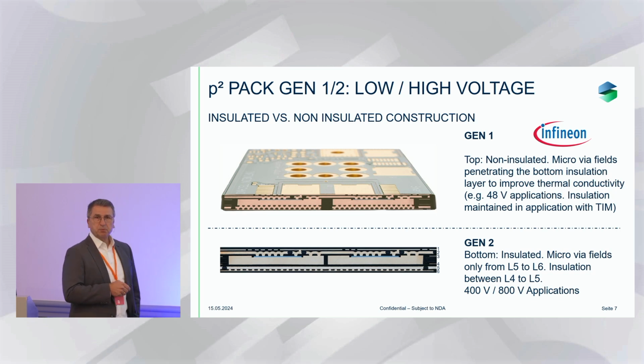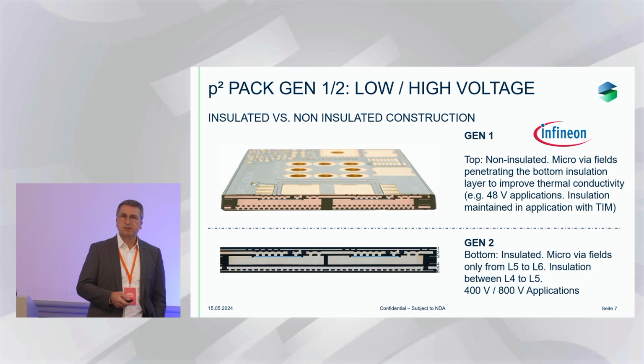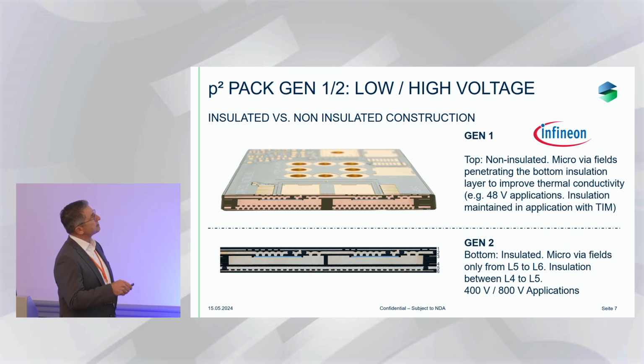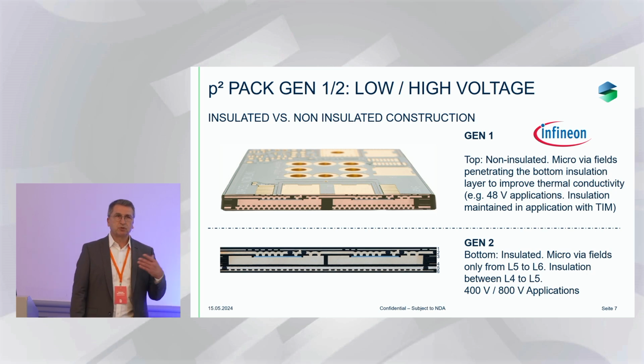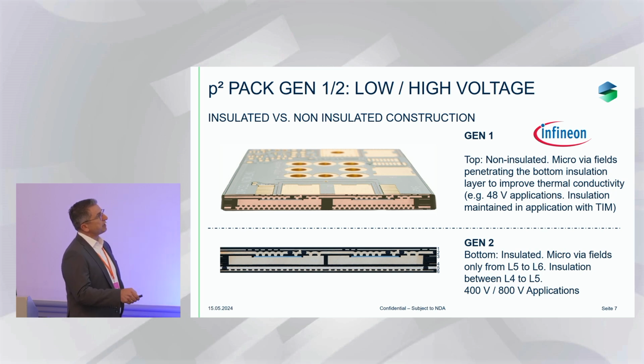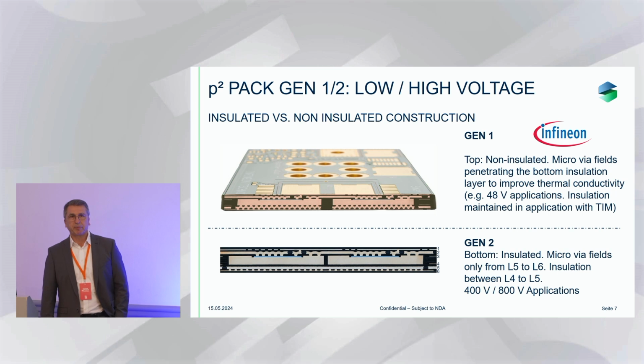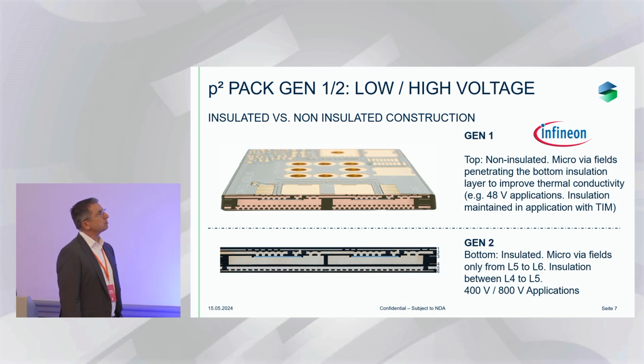So it is a non-insulated buildup. That means the drain potential is at the backside of the P-square pack. But this doesn't play a crucial role because in the assembly process, our customers take a thermal interface material which takes over also the insulation of the system. So in that case, the combination of non-insulated P-square pack and insulation with a thermal interface material led to the best thermal resistance. The second generation, which is in series development right now, is supposed to go into 400 and 800 volt electrical system applications, so major drive applications for the automotive industry.